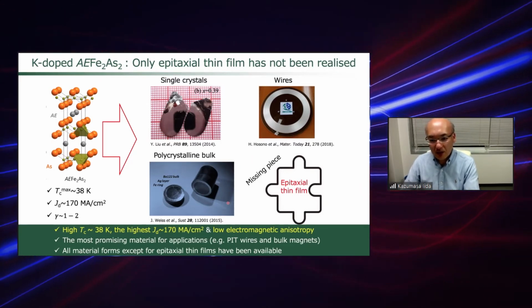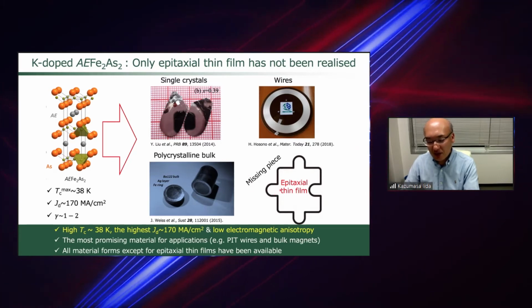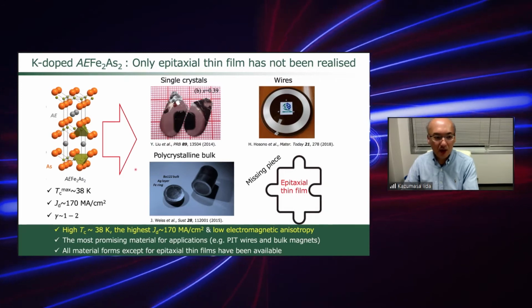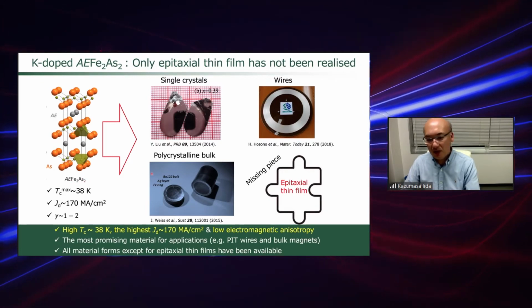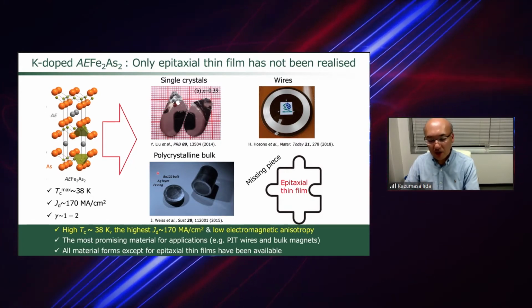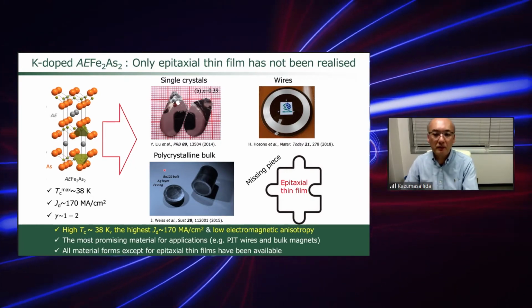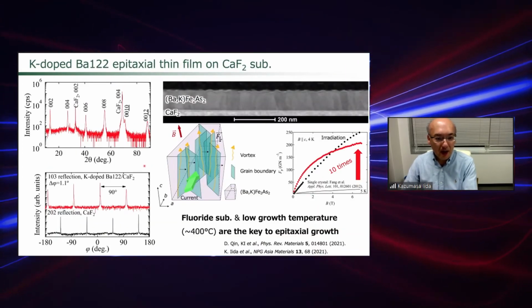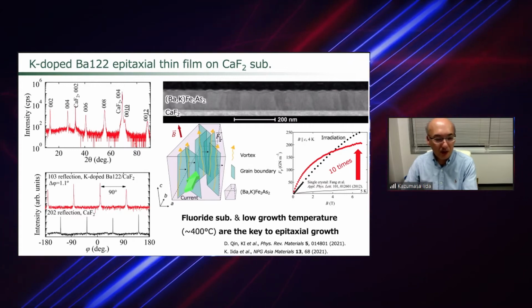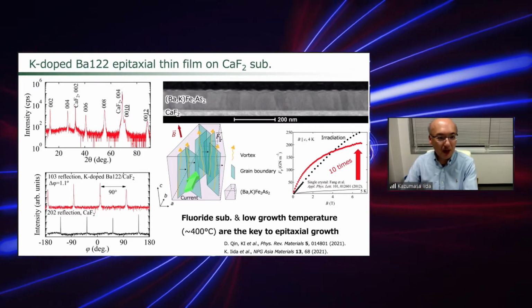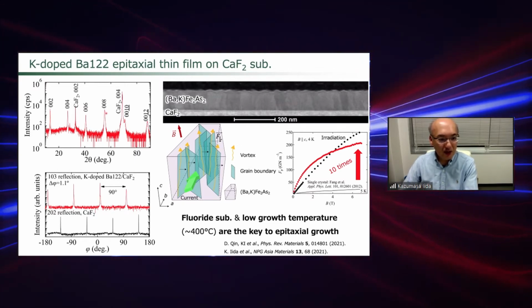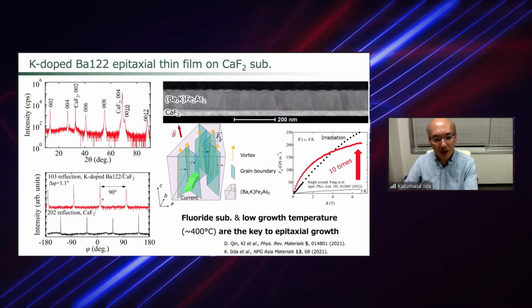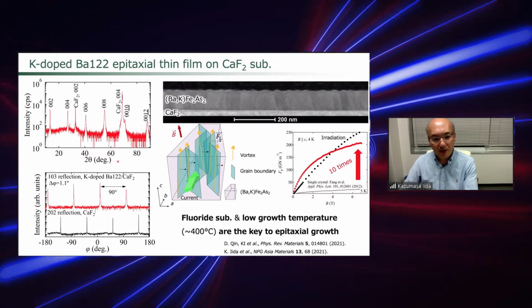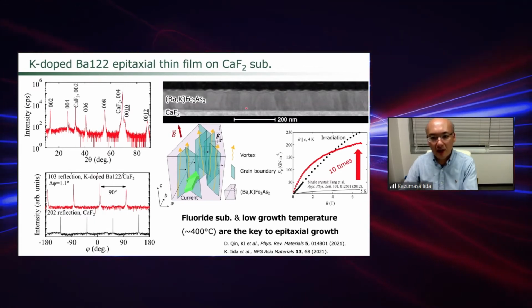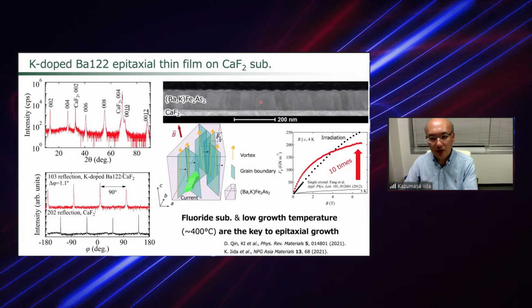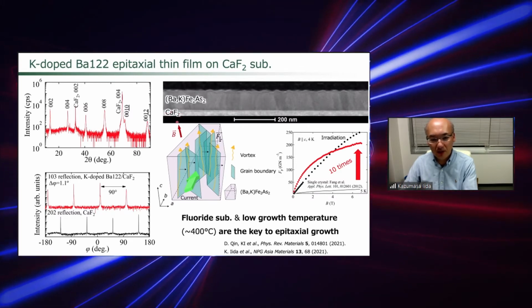Now, all material forms except for epitaxial thin films were available in the potassium-doped strontium or barium 122 systems, which is in sharp contrast to the other iron-based superconductors. But quite recently, we have successfully fabricated potassium-doped barium 122 epitaxial thin films on calcium fluoride substrate. Here is a summary of the structure characterizations by X-ray diffraction, and you see that it grew epitaxially. And this is a cross-sectional view of the potassium-doped barium 122 film grown on the calcium fluoride substrate.